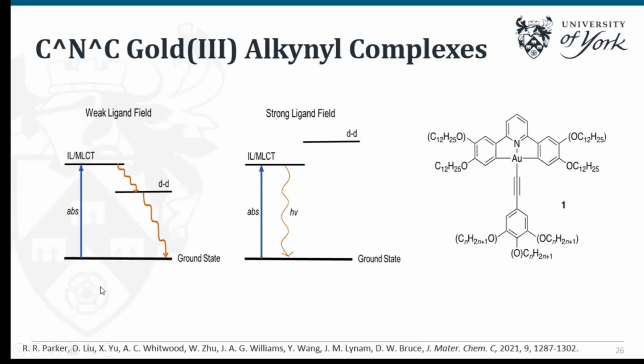It turned out to be due to the fact that in most gold(III) complexes, when you absorb light from your ground state up to your excited state, the easiest way for it to get back down to the ground state is actually via dd metal orbitals on the gold ion, without emitting light. So it'll just go up to that excited state and trickle down through this deactivating intermediate state.